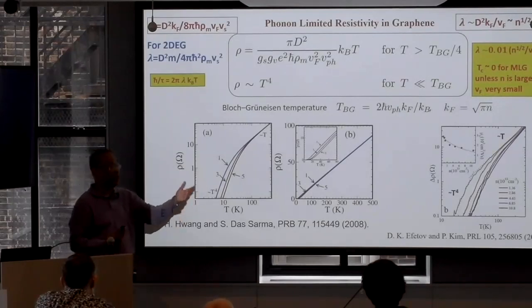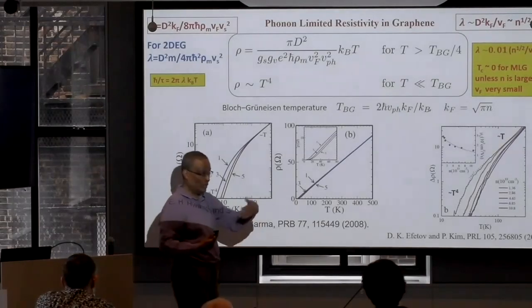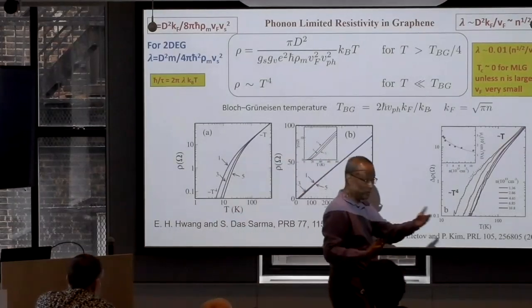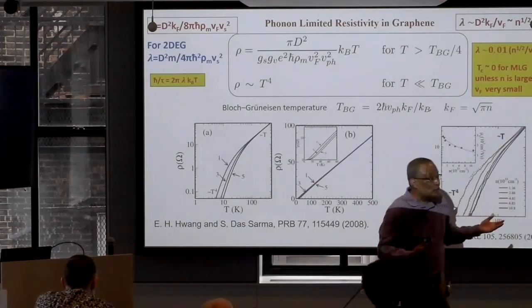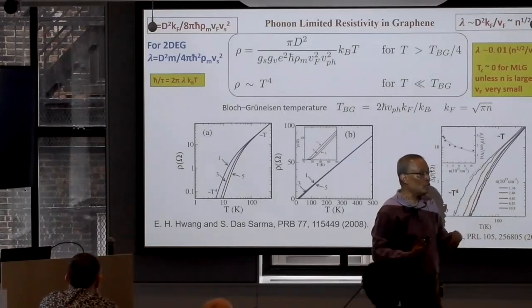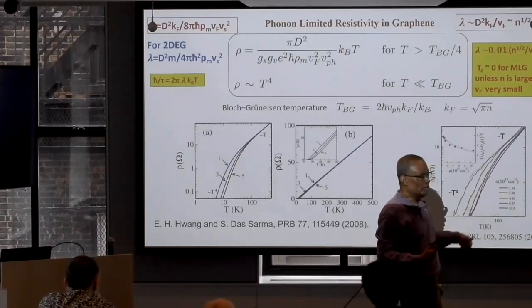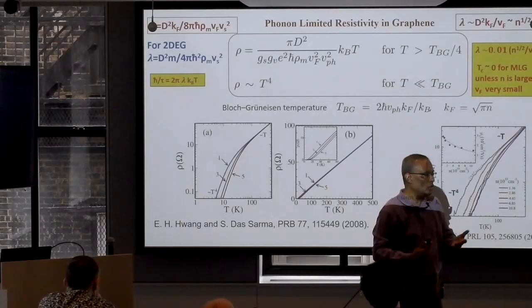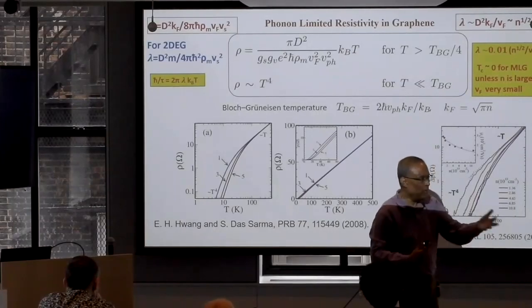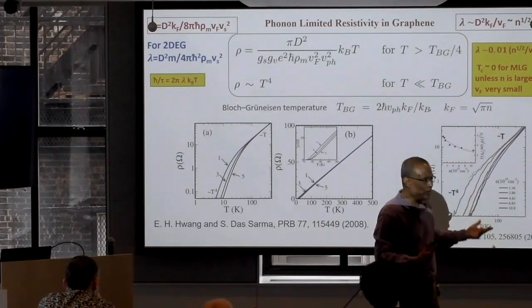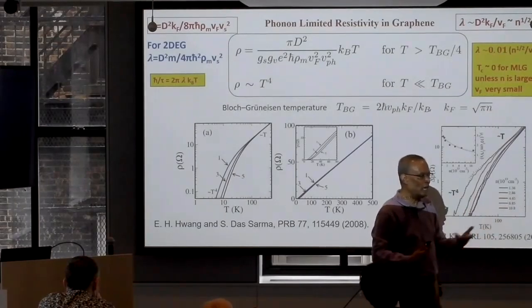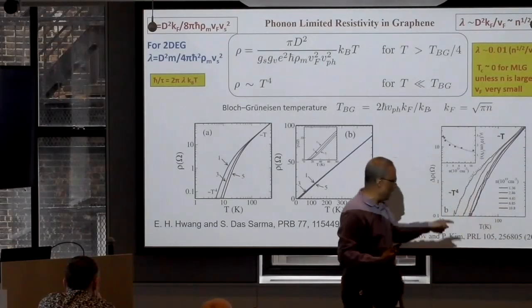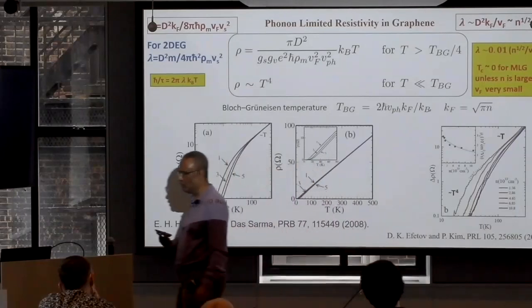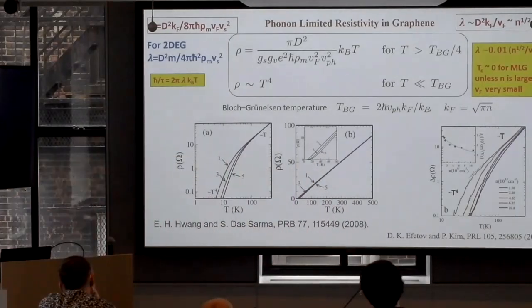And these kinds of things have been seen in holes in gallium arsenide and so on, because as you know, there could be linear in T dependence coming from disorder, and it's very interesting. And these things in gallium arsenide are reasonably well established. In graphene, disorder induced temperature dependence is not there because it doesn't have the Fermi surface anomaly, because it's Dirac, okay? So 2k disorder scattering doesn't have strong temperature dependence. It's not important. I don't remember the residual resistivity, but it was not an issue. But it's a good question. In some other materials, it could matter.